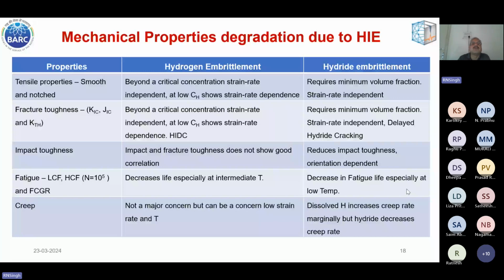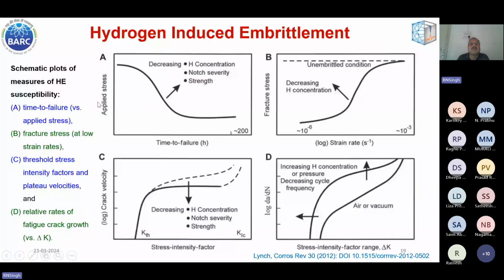Now here are some illustrations of hydrogen-induced embrittlement. If you see applied stress and time to failure, as the hydrogen concentration decreases, you can see this curve become almost horizontal. So this shows the effect of hydrogen: if hydrogen is present, even at low stress, this component can fail. The fracture stress also shows the effect of strain rate. At lower strain rate, toughness and fracture stress are very low. In the unembrittled condition you have this dotted line, and because of hydrogen, this has come down.